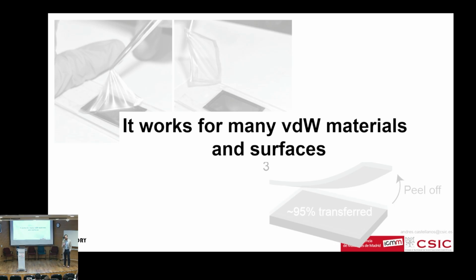So it seems that the Nitto tape adhesive gets sublimated somehow with this temperature. So we have done XPS measurements. Well, our collaborators in Rome have done XPS. If you anneal the samples at mild temperature in high vacuum for a long time, the samples are super clean. They have done these XPS measurements that are very sensitive to surface contaminants, and they are pretty much negligible.